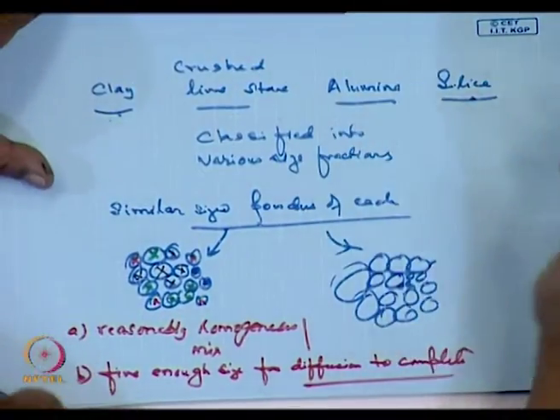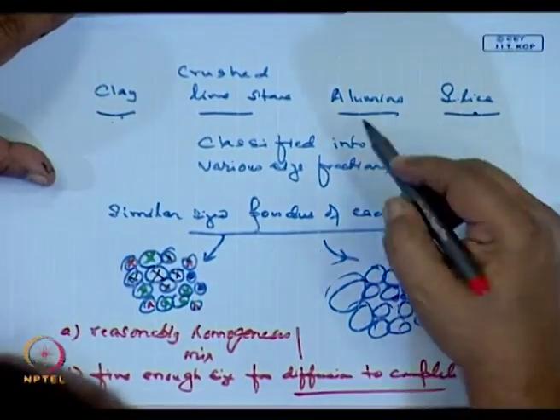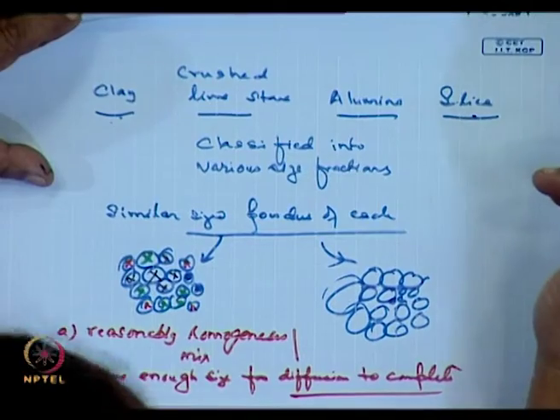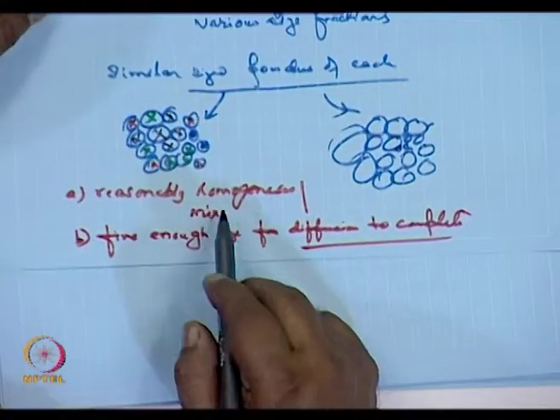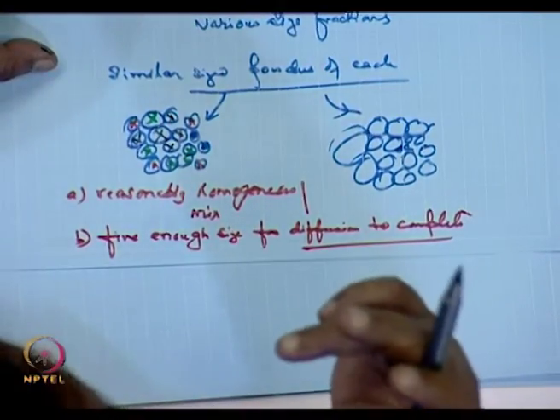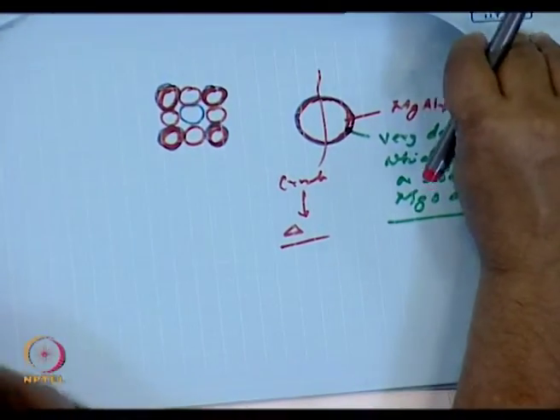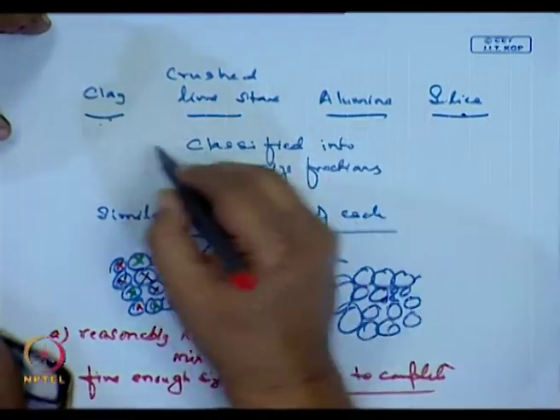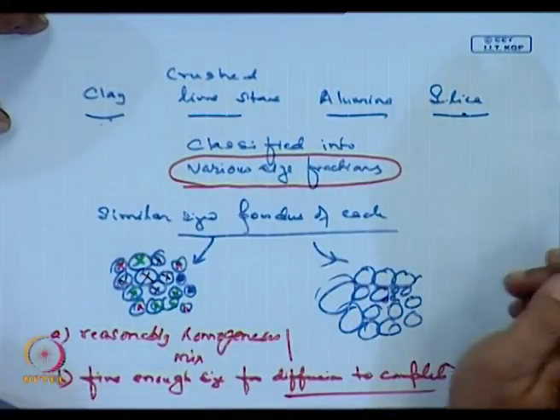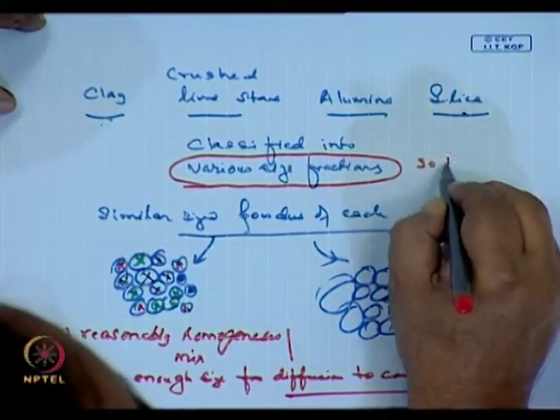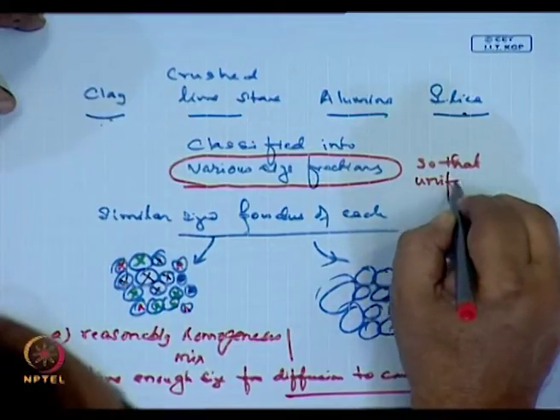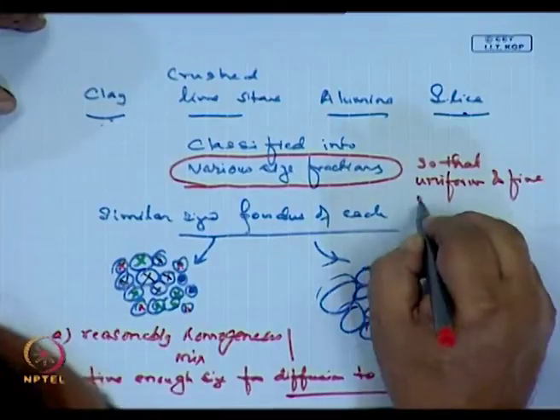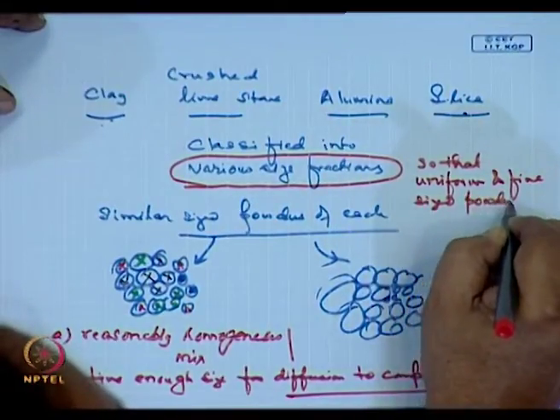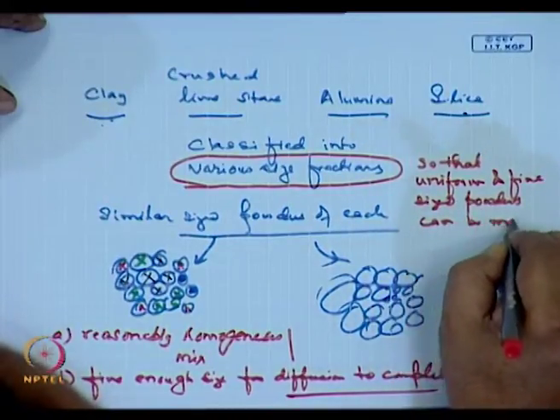Remember, I have got 4 different materials: silica, very hard; alumina, I can take from bauxite ore, which is less hard than silica; limestone is softer, and clay is somewhere in between. So, our goal is basically to have a reasonably homogeneous mix along with fine enough powders. When we are in this cement industry, let me come back to this. Each of these has to be classified into various size fractions. Why? So that uniform and fine size powders can be made to react.